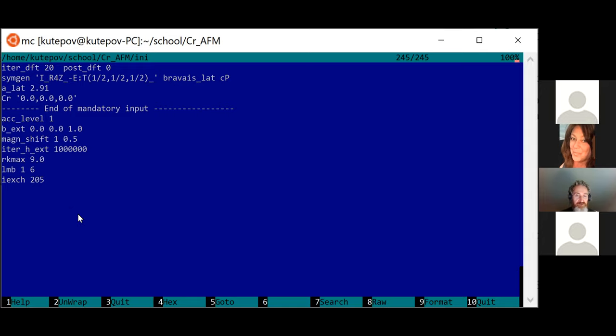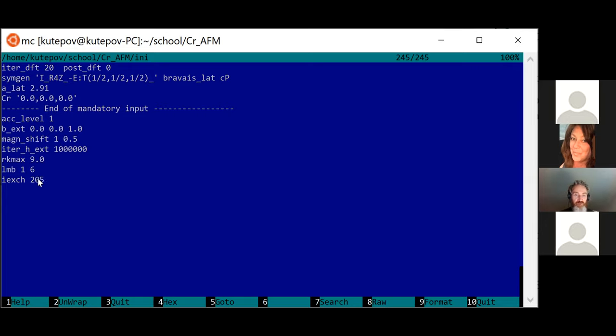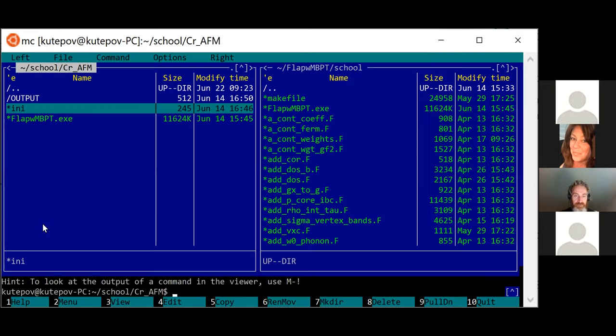The Bravais lattice is cubic primitive with the given lattice parameter, and you only provide one atom because the second is related by symmetry. This magnetic shift starts the spin splitting at the first DFT iteration. This is also a GGA calculation. I selected GGA because in the LDA case I believe there is no magnetization — it starts with some splitting and converges to zero — but in GGA there should be non-zero splitting.